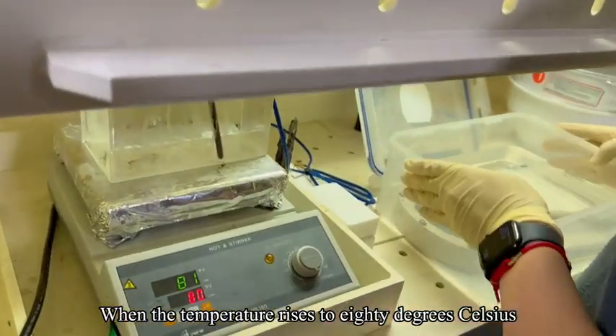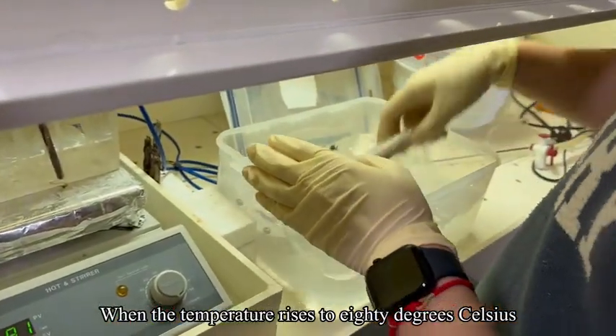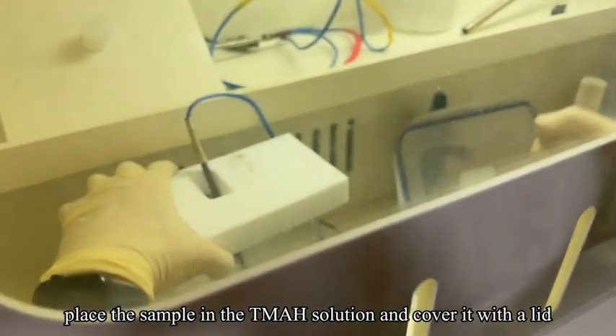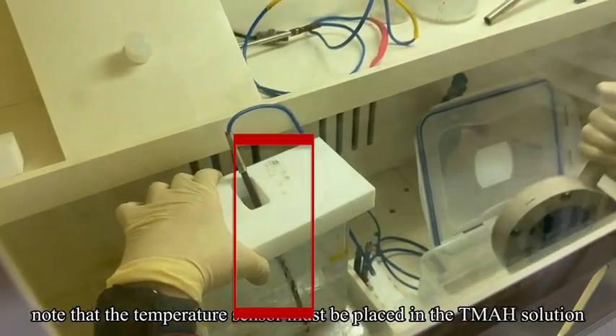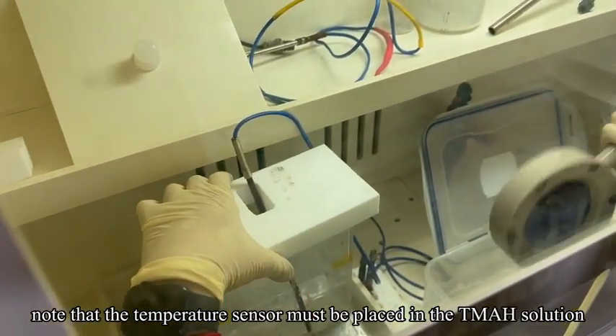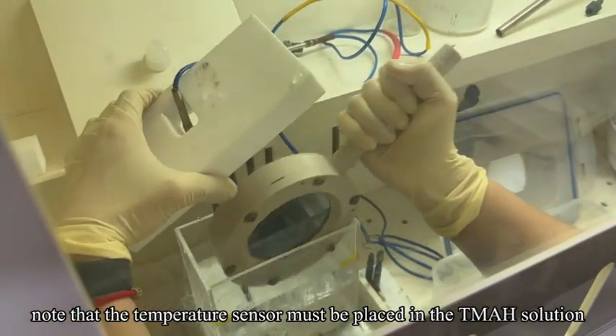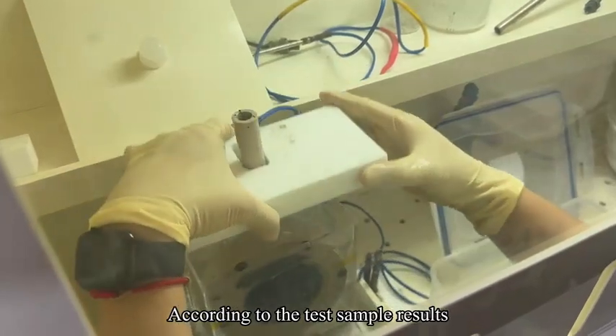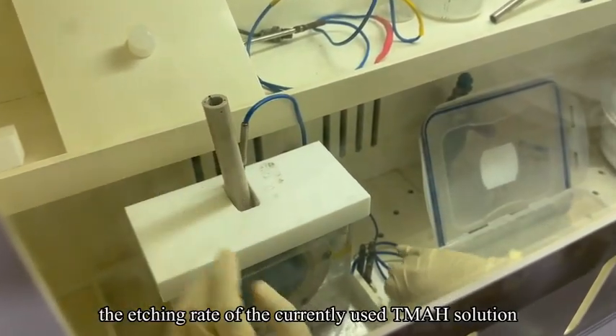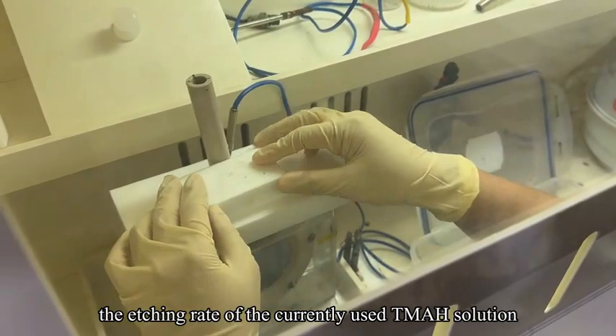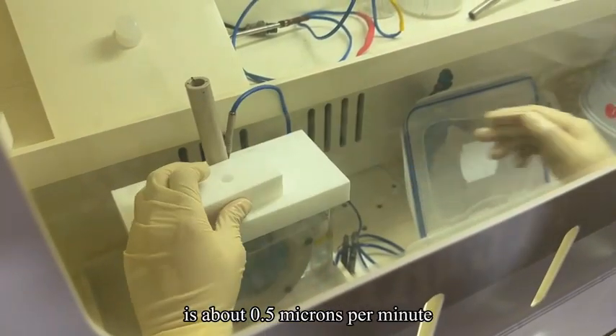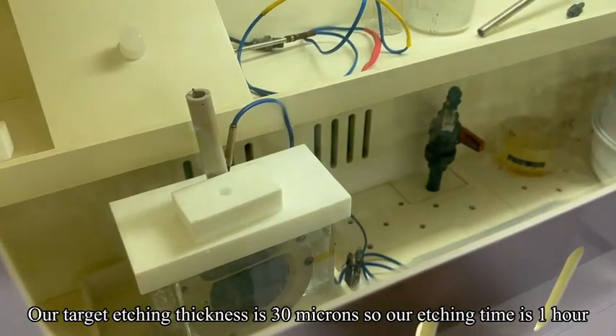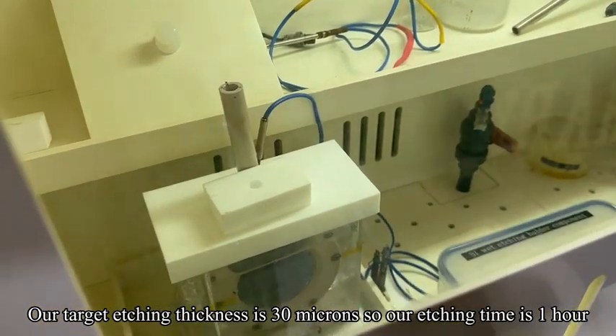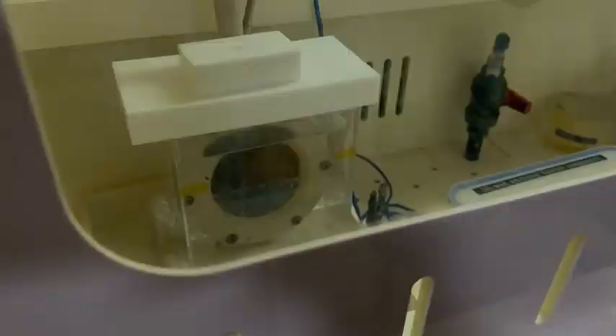When the temperature rises to 80 degrees Celsius, place the sample in the TMAH solution and cover it with a lid. Note that the temperature sensor must be placed in the TMAH solution. According to the test sample results, the etching rate of the currently used TMAH solution is about 0.5 microns per minute. Our target etching thickness is 30 microns, so our etching time is 1 hour.